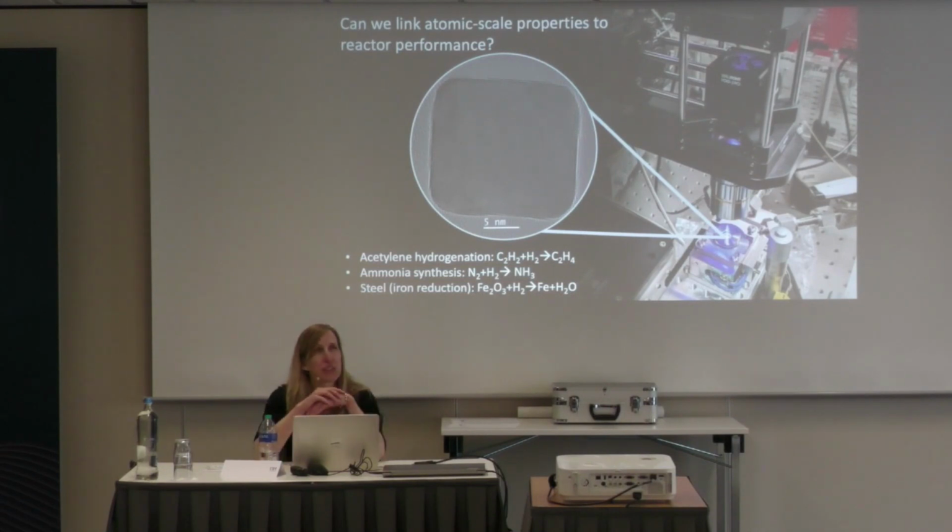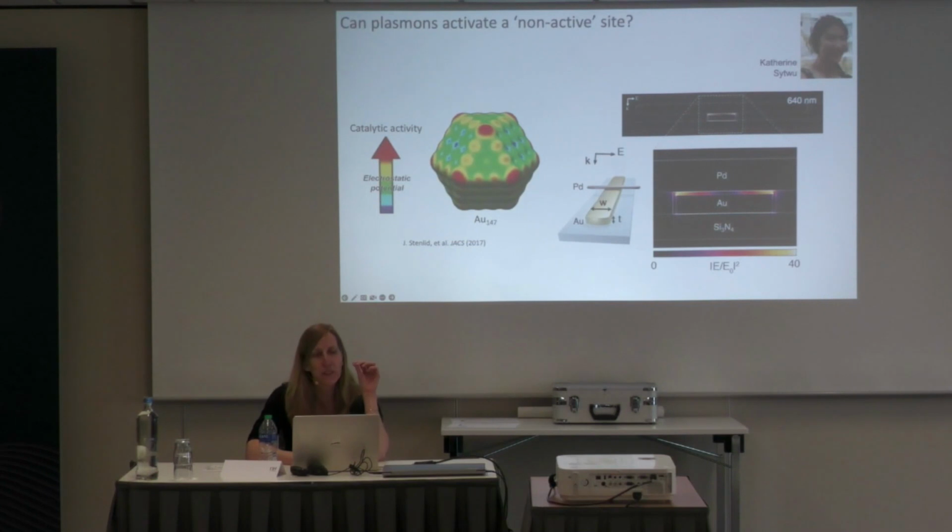Oh, yeah, that's a great question. So basically, if I go back to this slide, for most catalysts, the catalytic activity is always the highest at these low coordination number sites. And those just wind up being, at least for the catalysts we look at, the most preferred atomic rearrangements to have hydrogen split and then adsorb onto the palladium itself. Okay, and as it's the most reactive, it also dissolves the hydrogen faster.